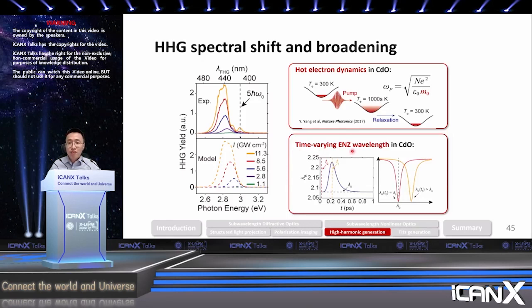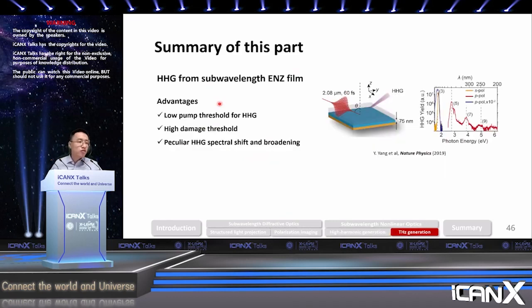One of the major potential applications of having this broadened spectral peak in the harmonic signal is that we can use this phenomenon to shrink the pulse duration of the harmonic signal in the time domain, such that we can get a very short pulse, for example, to generate an isolated attosecond pulse. So to summarize this part, we did high harmonic generation using this subwavelength ENZ field with a very low pump threshold, and the sample has a quite high damage threshold, and we also see this quite particular feature of high harmonic spectral shift and broadening.